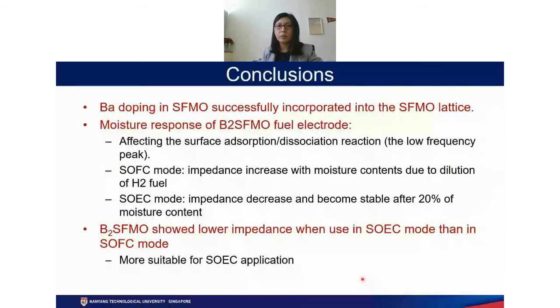Okay, so it comes to our conclusion. So by doping barium in the SFMO, we have shown that the barium can successfully incorporate into the SFMO lattice. And then the moisture response of a B2 SFMO fuel electrode is affecting the surface adsorption. Okay, so that's been seen very clearly. And then under the SOFC mode, the impedance increased with moisture content due to the dilution of hydrogen fuel. And under the SOEC mode, the impedance decreased and becomes stable after 20% of moisture content. Again, this is likely due to the amount of surface vacancies or defects that can take up a certain amount of moisture.